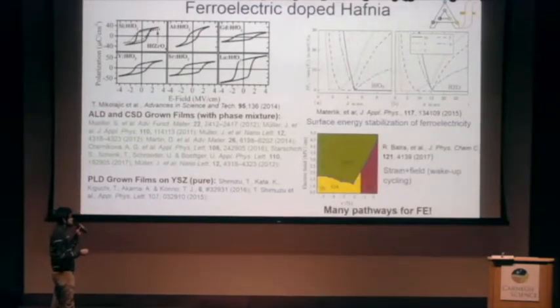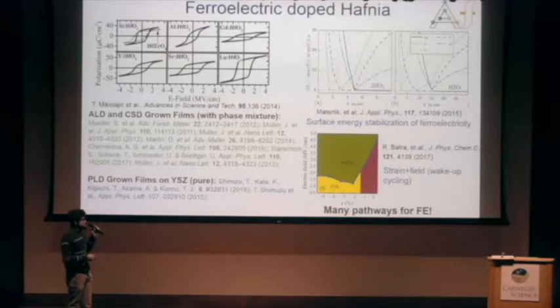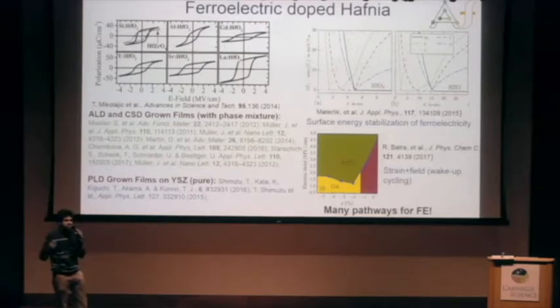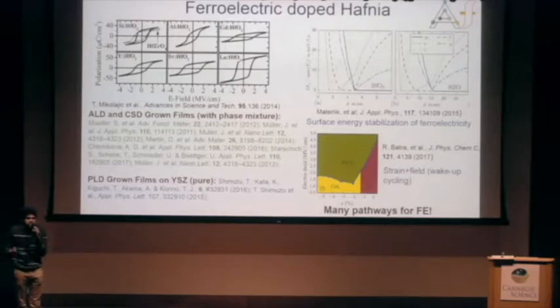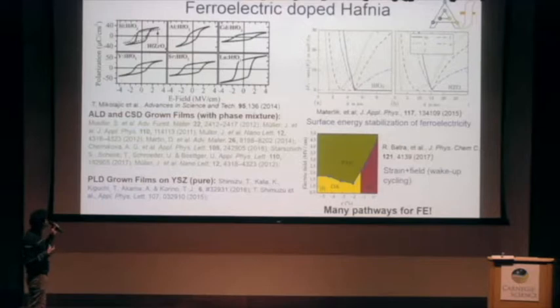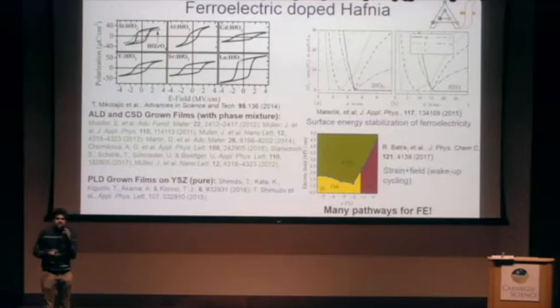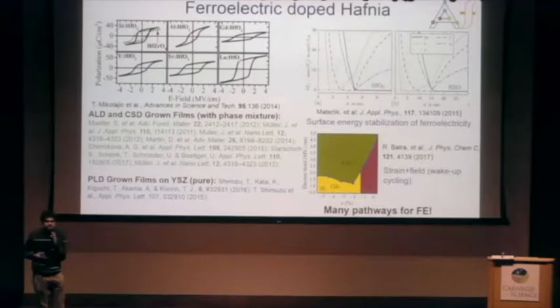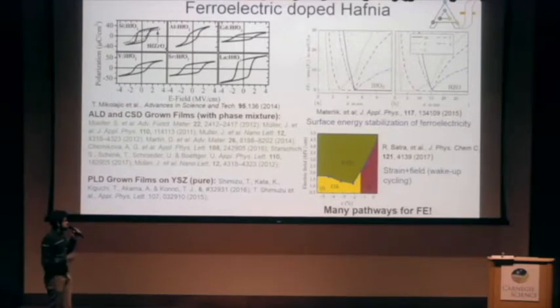Similarly, this group from University of Connecticut suggests that you could go to a polar orthorhombic phase by applying biaxial compression as well as electric field. So it looks like there are many pathways to get to this ferroelectric phase. However, the problem is that most of these films are polycrystalline, polyphase, so it's difficult to decouple individual effects experimentally and understand what the effect of each factor is on stabilization of ferroelectric phases.